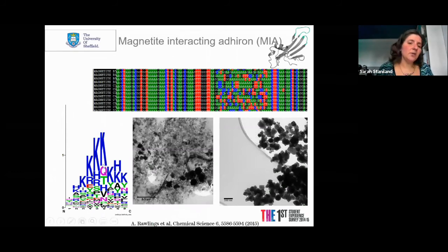and we pulled out a huge preference for lysine. So I've shown in blue the more basic residues. We've got lysine and histidine and arginine here that are shown as the Ks, the Hs, and the Rs. At different positions, these are the different positions on the variable region, there is a huge dominance of basic residues.